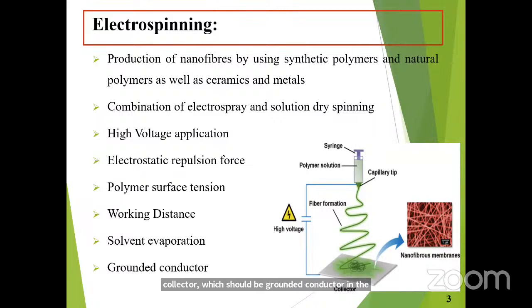In the first step of operating the procedure, fill the polymer solution in the syringe onto the machine by providing basic machine setup like the volume of the solution, flow rate, and syringe diameter. After this initial setup, high voltage is applied between the tip of the syringe and the collector. So through this process, we can produce the nanofibers of the polymeric solution. So in this current study, we use the electrospinning process to produce chitosan nanofibers for the desired application.